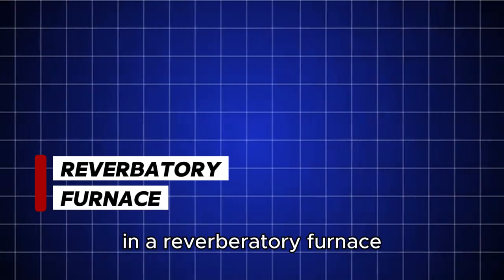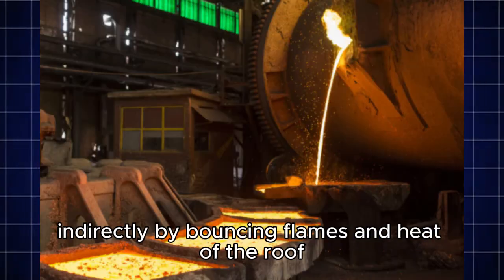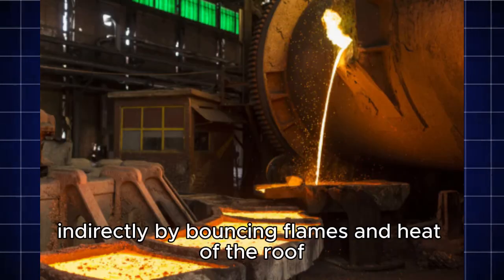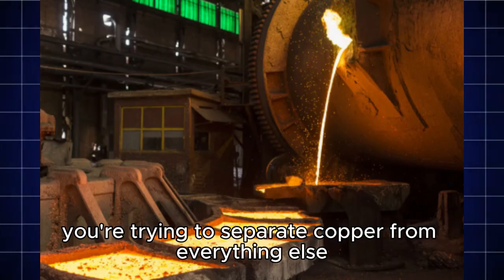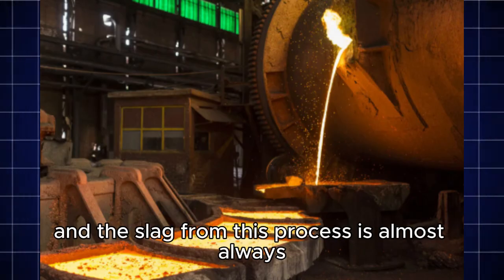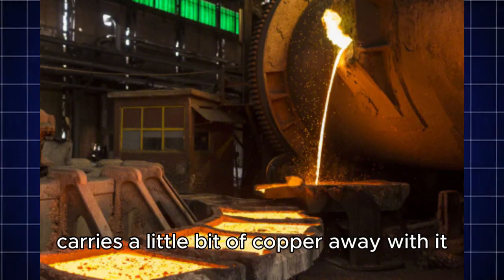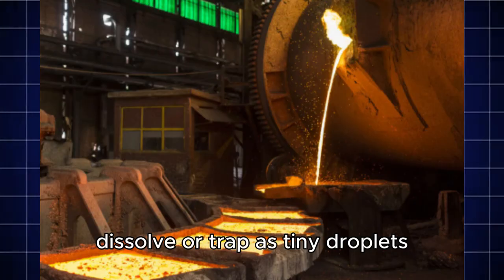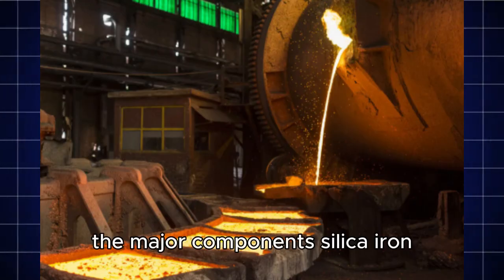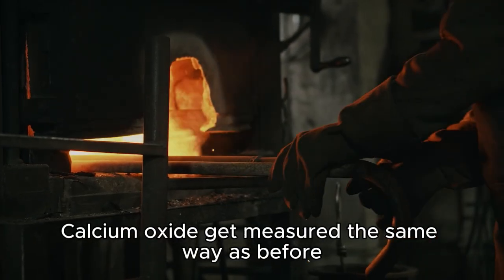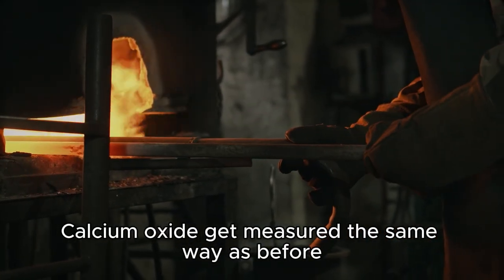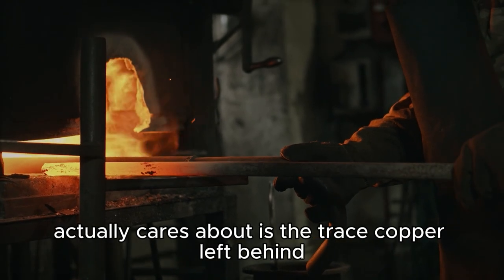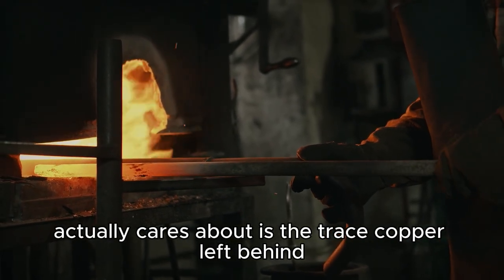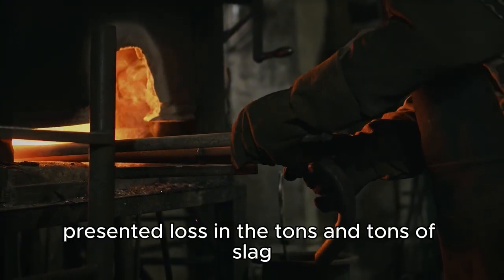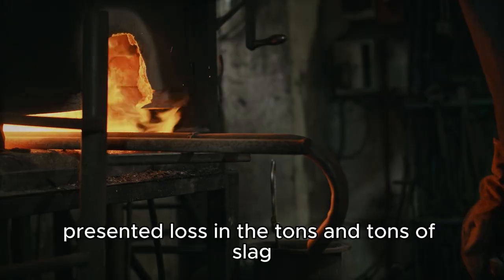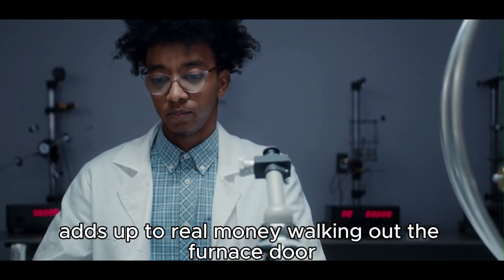In a reverberatory furnace, a furnace that heats the charge indirectly by bouncing flames and heat off the roof, you're trying to separate copper from everything else, and the slag from this process almost always carries a little bit of copper away with it, dissolved or trapped as tiny droplets. The major components, silica, iron, calcium oxide, get measured the same way as before, but the number everyone actually cares about is the trace copper left behind. Because copper is valuable, and even a small percentage loss into tons and tons of slag adds up to real money walking out the furnace door.